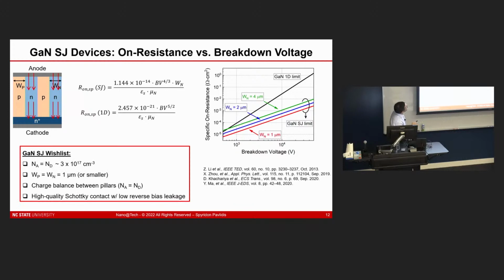When we went through and analyzed these devices for different geometries and so on, we can come up with these analytical equations to very quickly understand what the benefits of the superjunction device are. And you can now see what I was talking about earlier in terms of breaking that slope. That conventional 1D limit is here with that conventional relationship between breakdown voltage and Ron. And when we get to the superjunction, we see a new relationship, and that relationship has an extra tuning parameter, which is the pillar width.